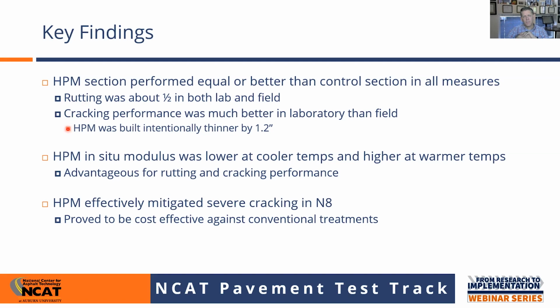Had they been built the same, we would have likely seen, based on the data, much better performance out of the high polymer section. I think the change in modulus is really important, that the fact that we're getting that bump on the high temperatures and it's a little bit lower on the low temperatures gives us a lot of good advantages in terms of rutting and cracking performance. And we were able to effectively mitigate that severe cracking in the other experiment in section N8. Without that, we were really scratching our heads about how we were going to fix this, because the problem was not really the asphalt materials. The problem is that we had built it on such a fragile, soft foundation that we needed something that was going to be able to bend a lot further without breaking. And this high polymer material is what did the trick for us in this situation.